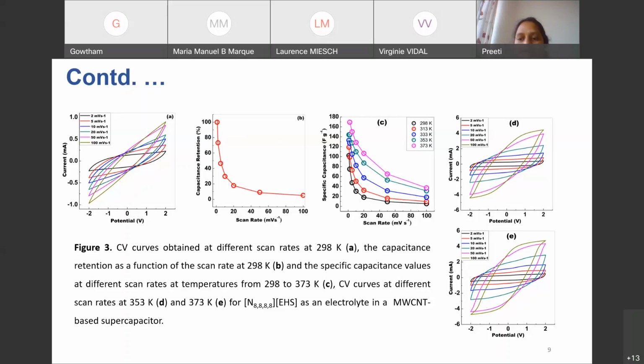and the ions are not completely moving towards the electrode surface. So that might be the reason we are getting a rectangular shape at room temperature at lower scan rate, but not at the high scan rate. Then we checked the CVs at higher scan rates and higher temperatures. When we increase the temperature, the rectangular shape remains even up to the higher scan rate. So that indicates that yes, it was the issue with the mobility of the ions.